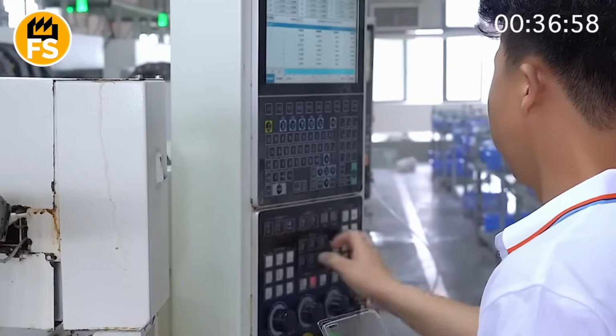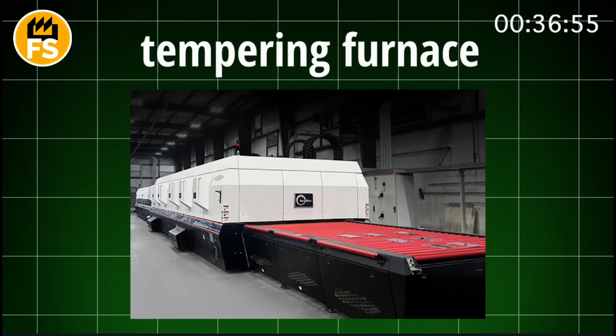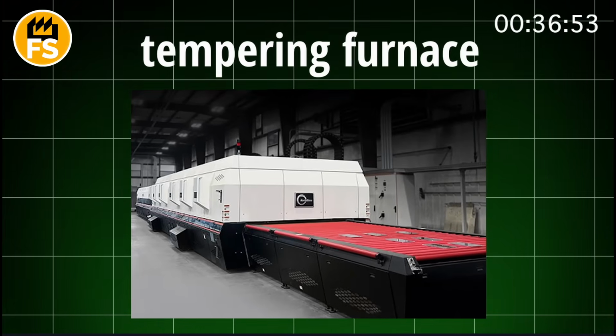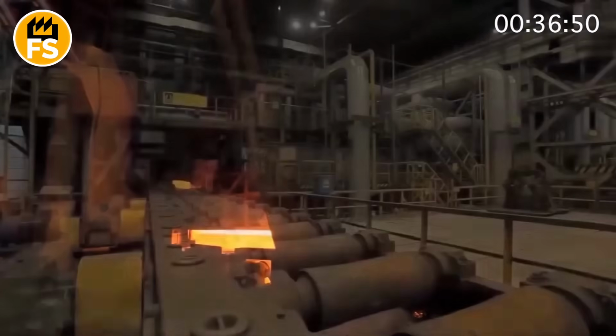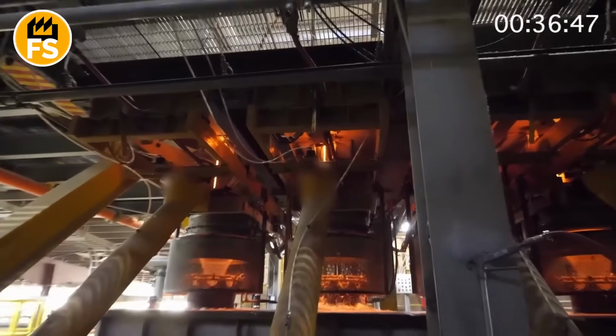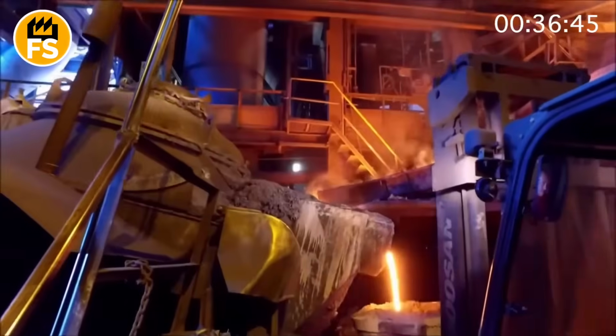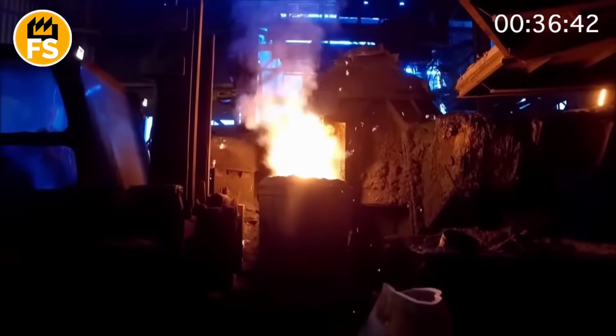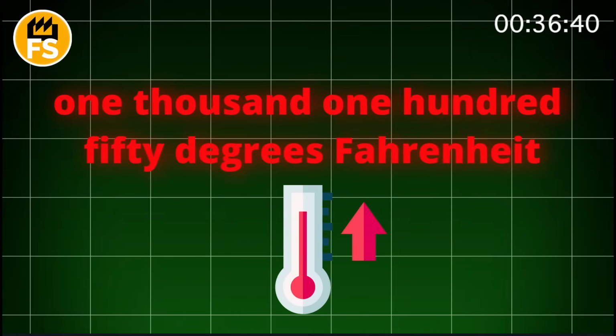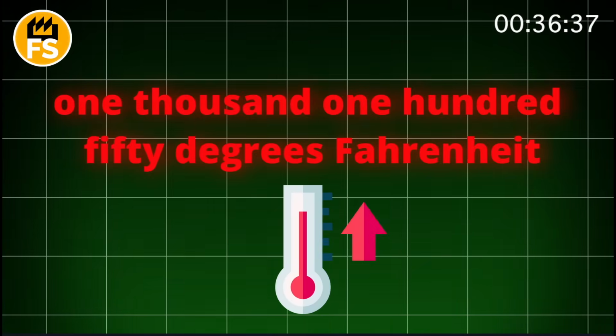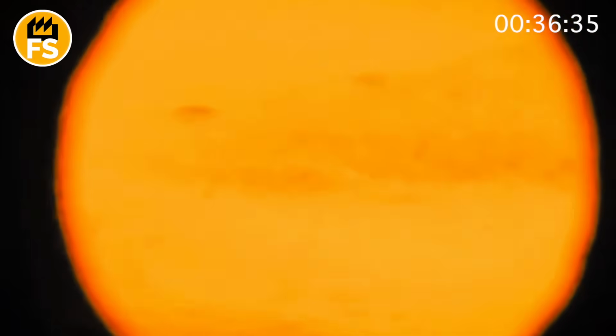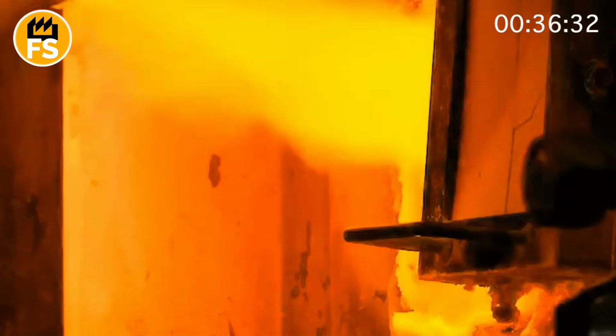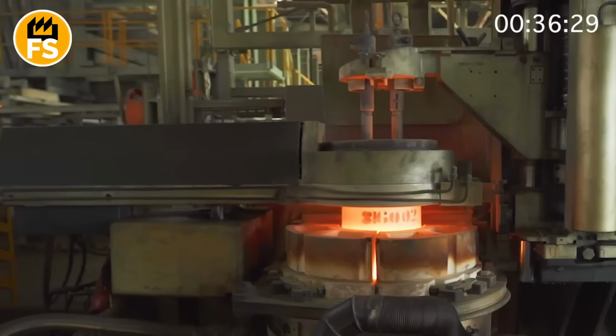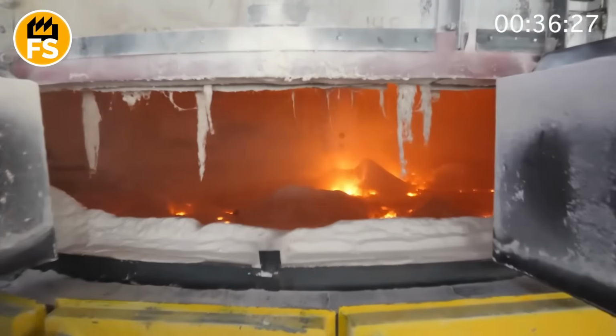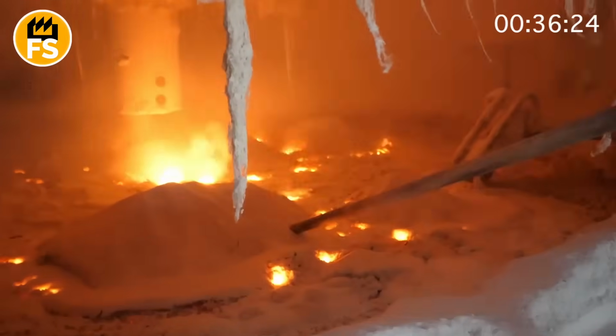When our glass recruit is ready, it heads to the main event, the tempering furnace. This is a long, low tunnel, red hot inside, with a series of ceramic rollers that form a moving track. The glass smoothly rolls onto these rollers and begins its journey into the very heart of the heat. The temperature inside reaches about 1,150 degrees Fahrenheit. This is hotter than most home ovens in self-cleaning mode. Inside, the glass begins to glow with an eerie orange-red light, like a piece of red-hot metal. It doesn't melt to a liquid state, but reaches its softening point.